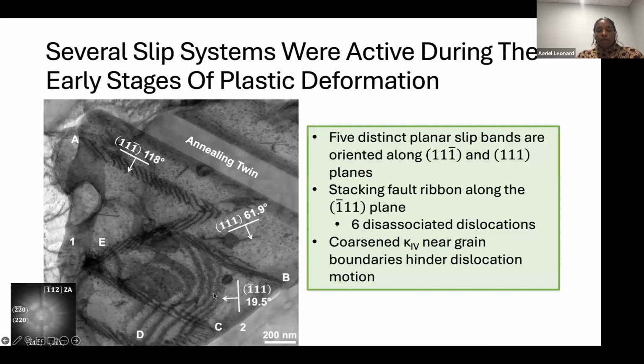Seeing the stacking fault ribbon was extremely interesting because, of course, we know that slip bands are going to occur in the material, but after combing through the literature for months, we had never seen someone report stacking fault formation in this material. We had not seen stacking faults or any mention of stacking faults, even in some of the newer literature from 2020 and 2023. So that was at the top of our heads: hey, we're seeing stacking faults, some interesting things are going on.